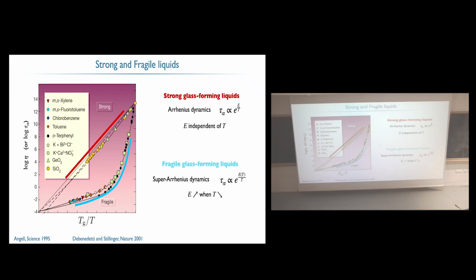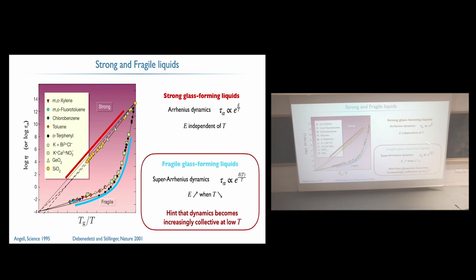And this is what I showed in the past slide. So here what you see is that as you cool the temperature, in this log tau versus 1/T, you don't have a straight line. You have something that is increasing. So it's as if you had Arrhenius dynamics, but the energy barrier now increases when the temperature decreases. So the E here, the apparent activation energy, is the local slope. You see that at first it's not so large, and then it increases, and at some point, well, you hit the glass transition.